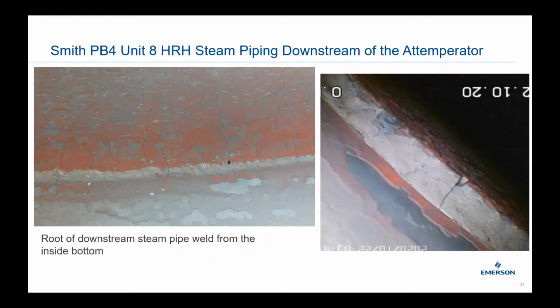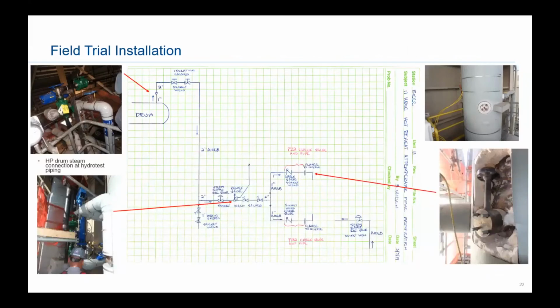Next slide. So this was the initial drawing for the field trial and a couple of photos. Of course, with a steam atomizing attemperator, you have to have a higher source of steam to create this pressure drop to atomize that incoming spray water. So for us, we were able to use our HP system, and we tapped into the steam coming out of the HP drum. That provided the pressure needed, and the temperature was low enough where we could use carbon steel to minimize some of those project costs.